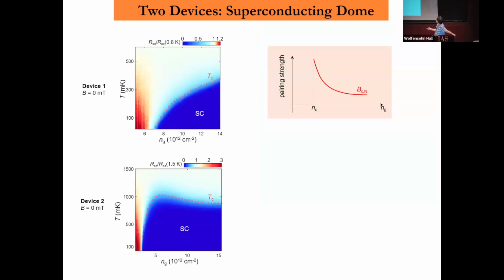I'll use the last 10 minutes to quickly go through some new findings that we have. One thing is, as I mentioned, if you look at TC, you think, oh, TC goes down like this, in device 1 here. But if you look at Nernst, the fluctuation, I already told you, in the same device, you actually see something rapidly increase, which is the order parameter, the pairing potential of the superconducting state.